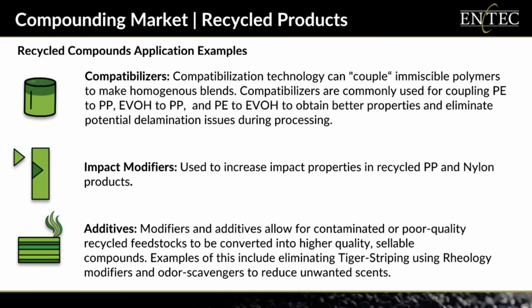Another example is using an impact modifier to boost the properties of a recycled polypropylene. After seeing multiple heat histories, the polypropylene feedstock can lose properties, especially impact and elongation, and become more brittle. Incorporating even a small amount of impact modifier can help to improve the final compound by boosting the impact and toughness and elongation properties. Going even to higher levels would actually improve those properties even more.